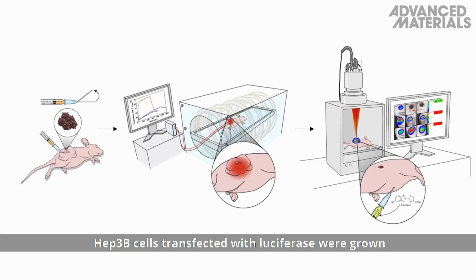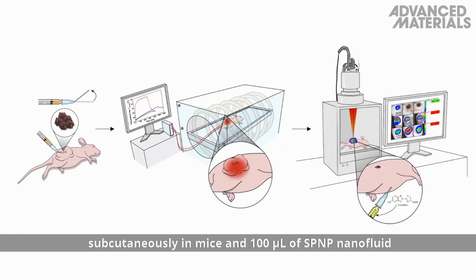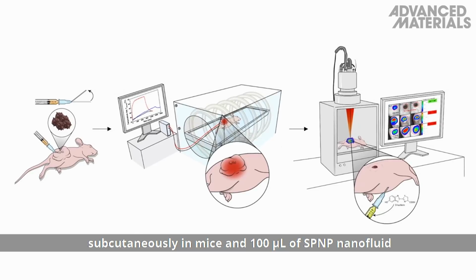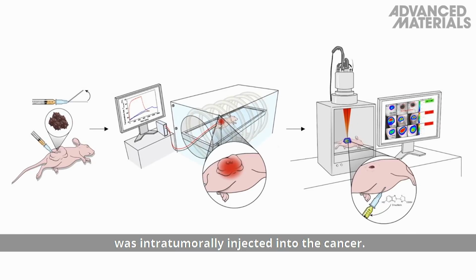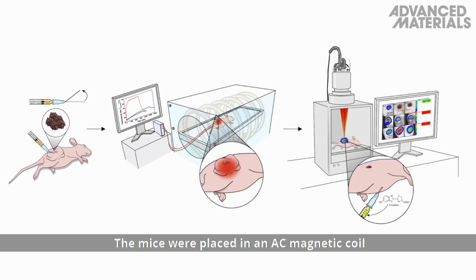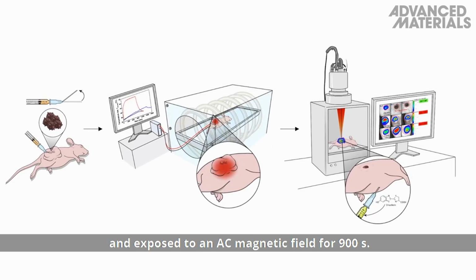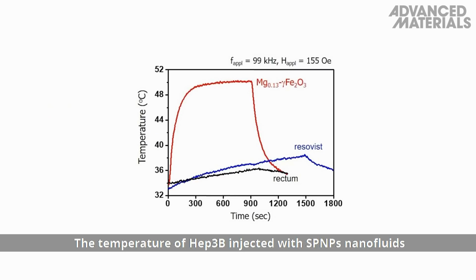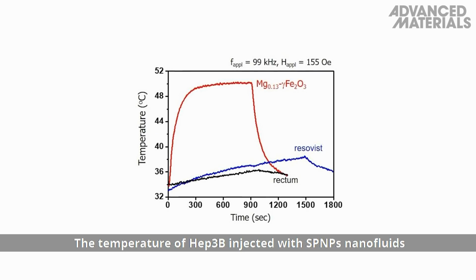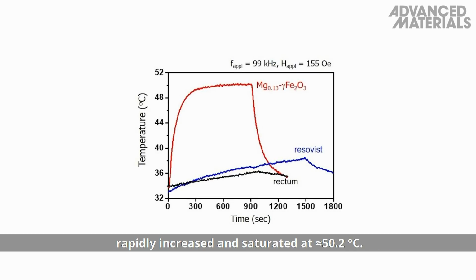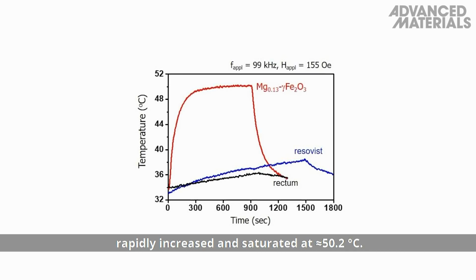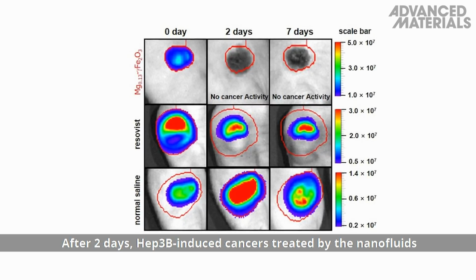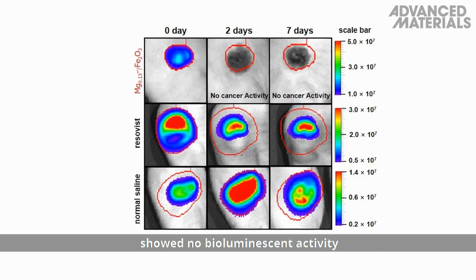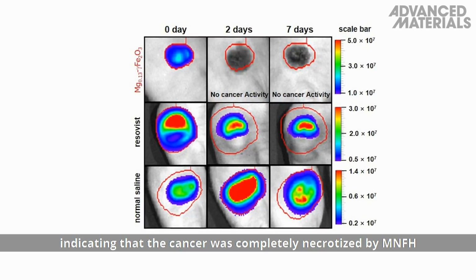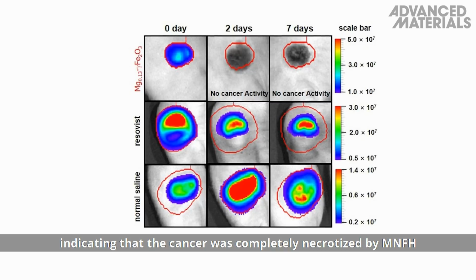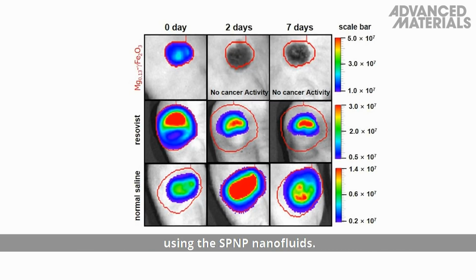HEP3B cells transfected with luciferase were grown subcutaneously in mice, and 100 microliters of SPNP nanofluid was intratumorally injected into the cancer. The mice were placed in an AC magnetic coil and exposed to an AC magnetic field for 900 seconds. The temperature of HEP3B injected with SPNP nanofluids rapidly increased and saturated at approximately 50.2 degrees Celsius. After 2 days, HEP3B-induced cancers treated by the nanofluids showed no bioluminescent activity, indicating that the cancer was completely necrotized by magnetic nanofluid hyperthermia using the SPNP nanofluids.